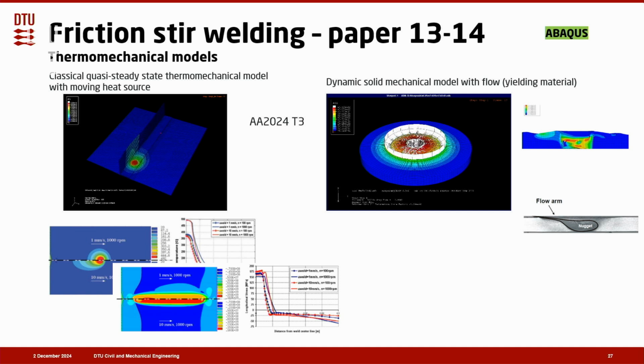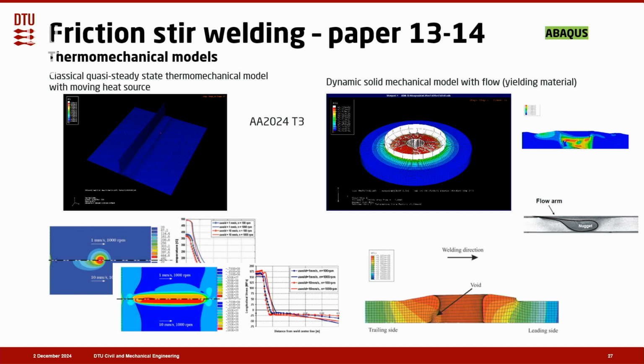We could predict the so-called flow arm, and we could also predict a void there that could lead to some tunnel defects, and so forth and so on. These models are actually multiphysical. That means that they take a lot of calculation time. They are complex. So we tried and think, okay, can we make a simpler model? And then we suggested the thermal pseudo-mechanical model.